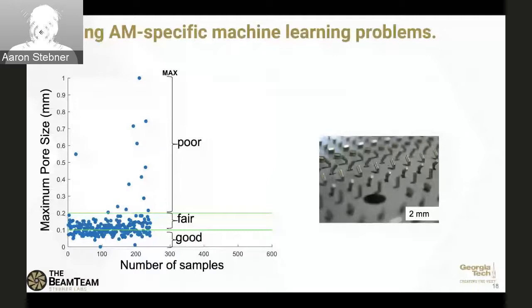But the good news was the way we were able to go about it was to change it from an attempted regression problem where we wanted to say how big the pore was, exactly what its effect on yield strength and modulus would be, and kind of get very quantitative. We weren't going to get there because they were outliers, but we were able to get to kind of a pass, fail, or check into this further metric for the companies. So kind of think about a green light, yellow light, red light. Just by turning these into classes and just binning everything, every defect that was 10% or more, 5 to 10% or less than 5% of the size of the minimum feature. So these are 2 millimeter diameter pins, and we draw the line there at 200 microns and 100 microns to make the classes. And that did give us enough data then to be able to classify when we would have a fail based on position and orientation. Okay, so let's go to the next slide.